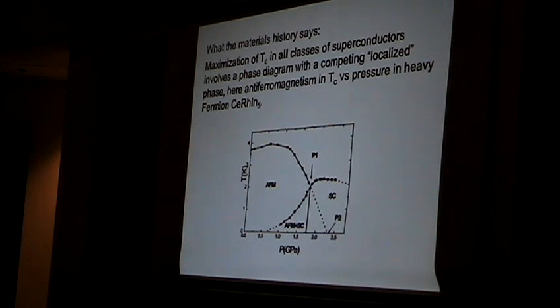But when we came to the case of heavy fermion materials, it turned out that all the superconductors, as near as we can tell, seem to lie in the vicinity of some quantum critical point, a magnetic quantum critical point in this case. But the argument I want to make is that if you look around in a broader set of superconducting materials, you can make an argument that all classes of superconductors seem to involve a phase diagram with a competing localized phase.